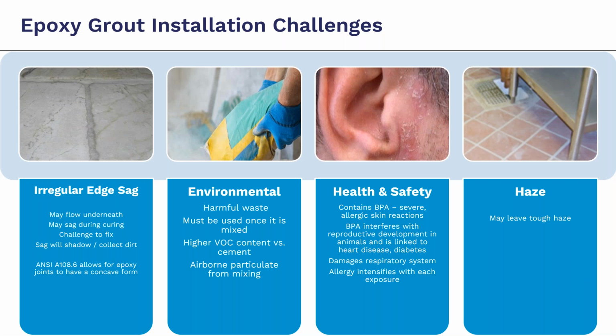With epoxy grout installation, it has challenges as well. It does have an irregular edge sag, so it may flow underneath. It could sag during the curing. It can be challenging to fix because the sag will shadow. It will also collect dirt. ANSI A108.6 allows for the epoxy joints to be concave form, which allows it to be easier to manage some of those sag and flow underneath that you have.